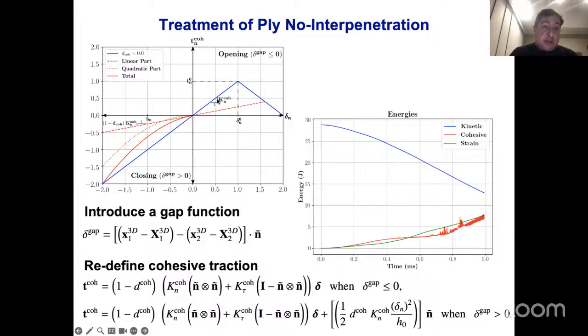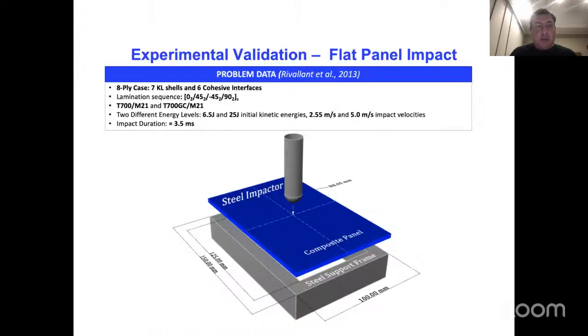And so then as a result, when you have full delamination, d goes to 1, the linear term in the penalty drops, but the quadratic term in the penalty picks up and precludes the ply interpenetration. And so what it does, again, it significantly improves the nonlinear convergence and the robustness in these calculations.